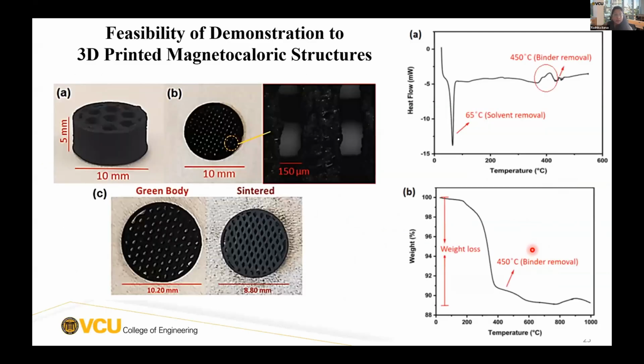What we have demonstrated is the feasibility to 3D print magnetocaloric structures with spatial resolutions as small as 150 microns. The structures that we have are isotropic, and when we see shrinkage within the microchannel structures, we see uniform shrinkage.